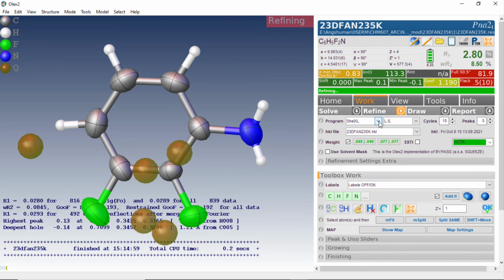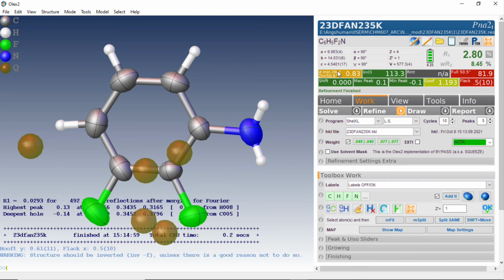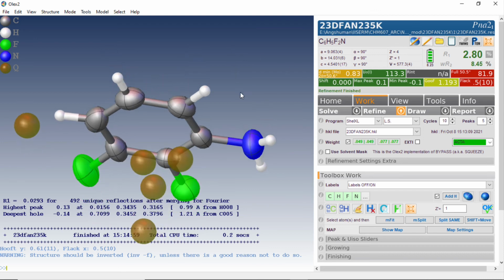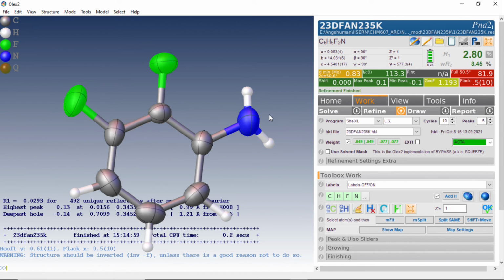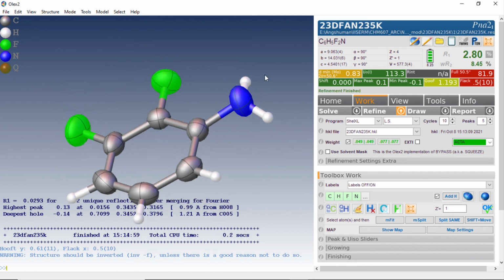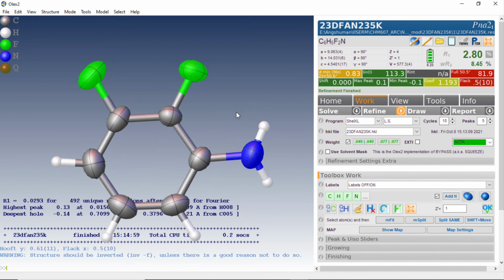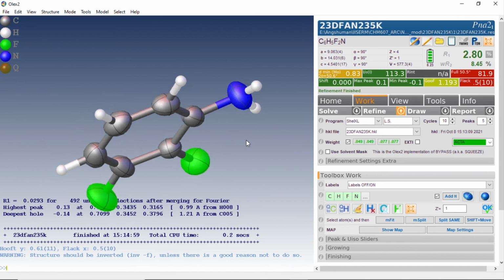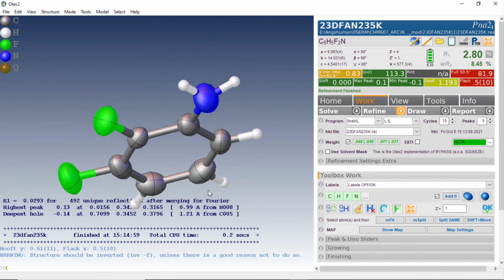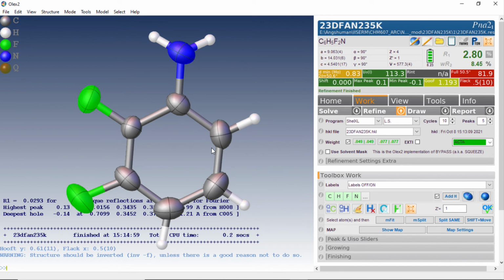The points which are orange or red here are the problem points, because the data is not a very good data, the crystal did not diffract, and the standard problem of in situ crystallization is that we cannot rotate the kappa during the measurement, and that is why the completeness is always less. But what we can show you here, the crystal data which was not possible to index using a normal procedure, the structure can be solved if we follow this method.